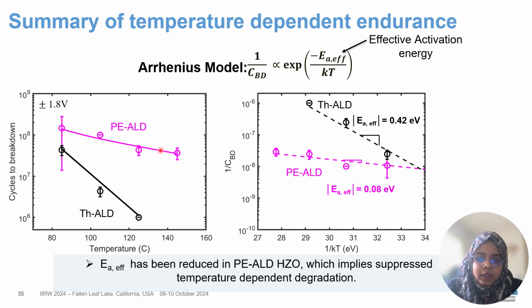Next, we have fed these cycles to breakdown versus temperature data into the Arrhenius model, which is shown here on the top. When we fit the data, the slope of this straight line will give us the effective activation energy, which is a measure of how much temperature dependent degradation we are having in each device. So the less the effective activation energy is, the more suppressed the temperature dependent degradation will be.